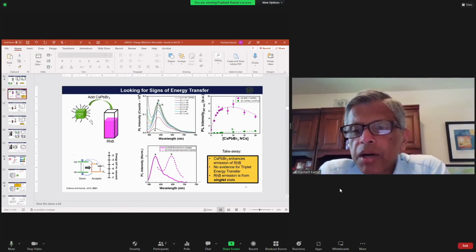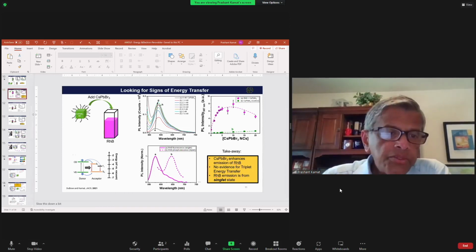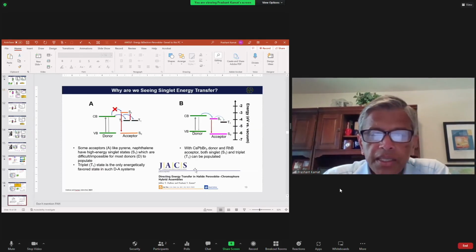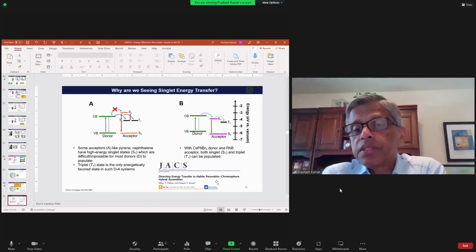Sometimes we use a small amount, maybe 1 to 2% polar solvent, to dissolve rhodamine B. If you see, the concentration of rhodamine B is in micromolar concentrations. They are not very high concentrations. In the previous study which I showed, they just took the crystals and sonicated them, and then they assumed that it is absorbing. But in our case, we did dissolve. The paper gives you all the details. Where is it? Yeah, here. This is JACS paper. We have given all the experimental details. There is another compound you can also try, with the thiocyanate, that binds much stronger than this one. Even 1 or 2 micromolar is fine to see this energy transfer.